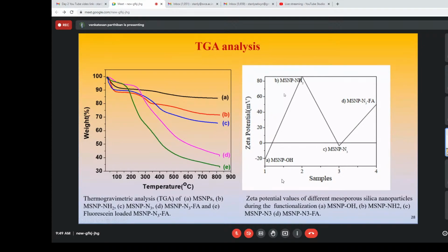After that we check the different functional groups we use. Here, the zeta potential of the mesoporous silica nanoparticle, initially the OH functional group, is negative, and after each functionalization we can see a positive and negative charge. So this is a confirmation of the material.